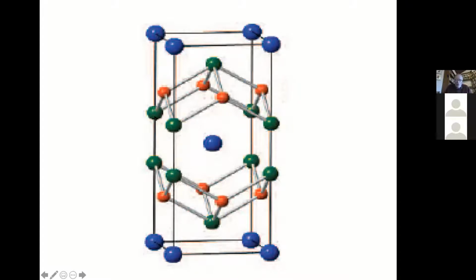It turns out that there's characteristically two different lengths that you get for this pnictide bond. There's a long length and a short length. You know, they're well separated. I think this was apparently first pointed out by Roald Hoffmann. And the idea is when they're closer together, you actually have a real bonding interaction. And when it's longer, this bonding is much less relevant.